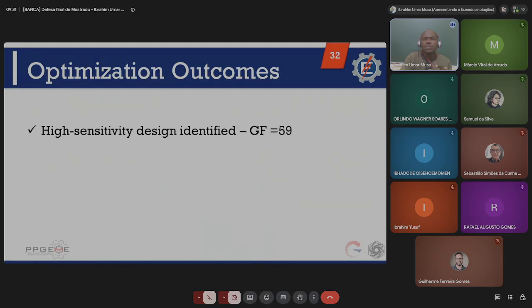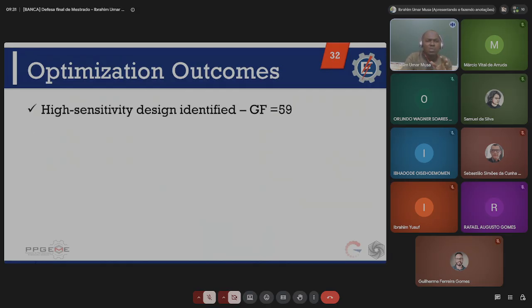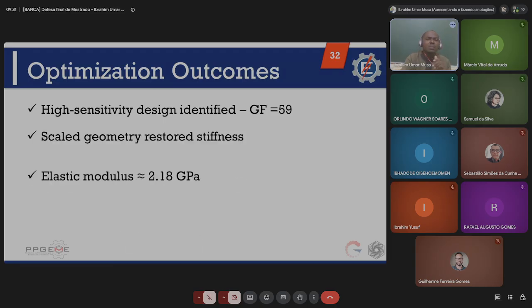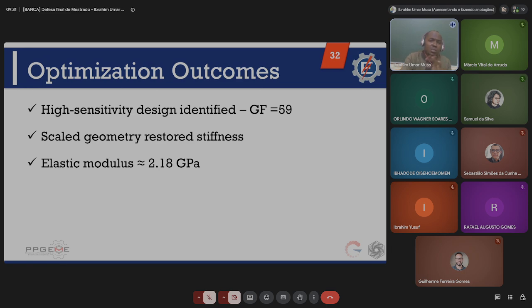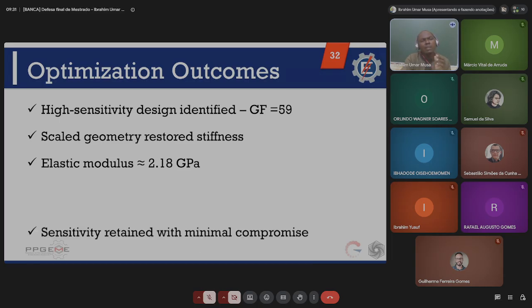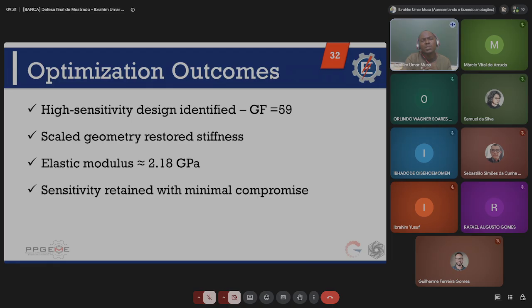And from the outcome of the optimization, we were able to see that the high sensitivity design was identified to be 59. And with the scaling, we were able to see that scaling also restores the stiffness with a value of 2.18 gigapascal, and that the sensitivity was retained with minimal compromise. And the validation error fell below 12% also for the scaled variants.